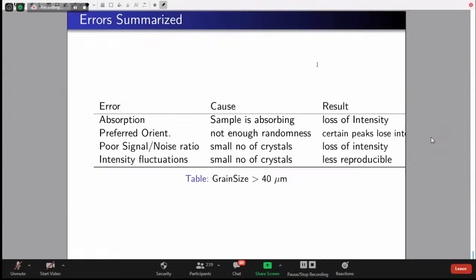Right. Here I just summarized all these different kinds of errors. So first one is the absorption part, which means the sample is absorbing. If you see, we are using copper K alpha, and if we go and use an iron sample, then we will have this trouble. The entire beam is going to be absorbed by the iron. Or if you use copper, you will have trouble with copper samples with a copper target. So this is because it is absorbing, and what happens is you will lose the intensity.